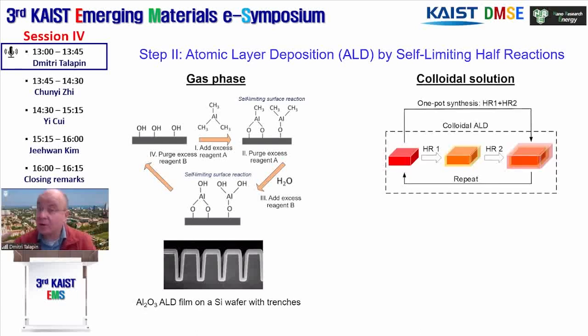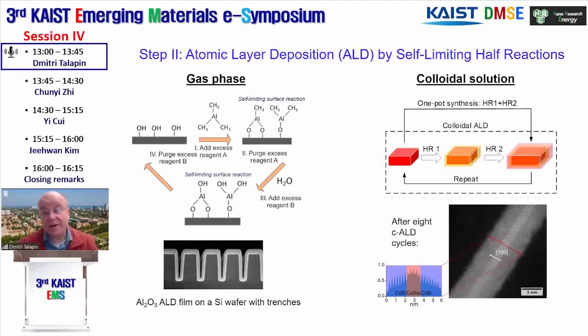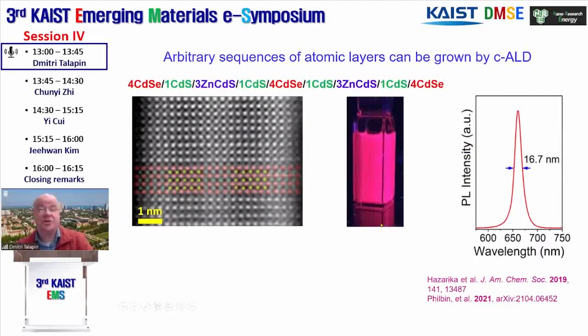What we proposed to do for colloidal science was to implement pairs of self-limiting half reactions for synthesis of colloidal nanostructures. And the idea is to grow layer after layer by what we called colloidal atomic layer deposition. That allowed us, for example, by completing 8 layers of colloidal ALD, to put 8 layers on each side of the structure. And again, if we have atomic precision after the nucleation stage and couple it to this atomically precise growth, we can grow pretty complex structures. Like in this case, we started with central platelets and then grew 1 layer of cadmium sulfide and 3 layers of cadmium zinc sulfide barrier layers and another interfacial layer of cadmium sulfide, and finished with quantum wells of cadmium selenide on the other side.